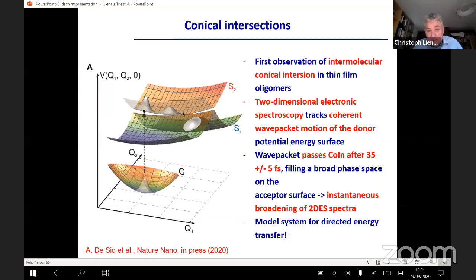this organic thin film. So we have observed for the first time, and the results have just been accepted in Nature Nano, an intermolecular conical intersection in a thin film oligomer. We have used two-dimensional electronic spectroscopy to track the coherent wave packet motion on the donor potential energy surface. And most interestingly, at least for us, we have really seen dramatic changes in the spectrum as a consequence of the rushing of this wave packet through this conical intersection.